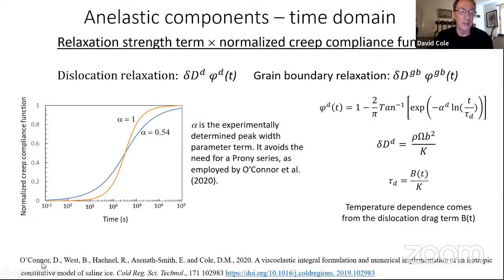My colleague at CRREL, Devin O'Connor, a numerical modeler, basically implemented my constitutive model in Abaqus. Unless you write a user-generated subroutine for the material behavior, you're stuck with what's called a Prony series approach, where you determine a number of specific relaxation times, a spectrum thereof, that each have this single mechanism behavior. It takes about 10 of them to reproduce what ice is doing. It's a way to handle this numerically, but if you're trying to develop analytical expressions where you want to go back and forth between frequency and time domains without a big numerical process, this use of the peak broadening term is the way to go.